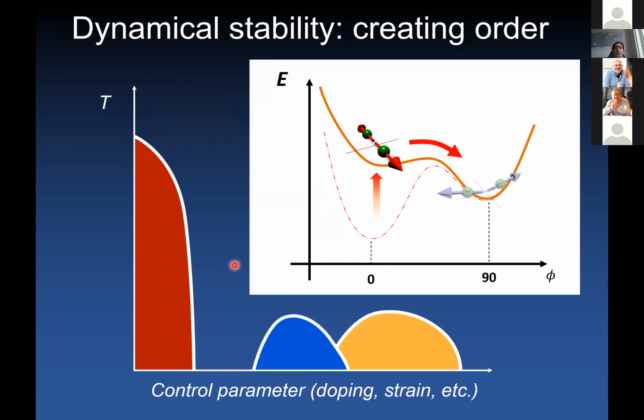Another idea is to induce dynamical stability. So if now you couple your radiation with low energy modes of the system that define the ground state, it is possible to directly change the profile of your configuration potential of the system, and therefore render a state metastable and favor phase transitions towards a competing state of matter. So a driven system, in principle, has access to new types of ground states that are generated by dynamical stability.